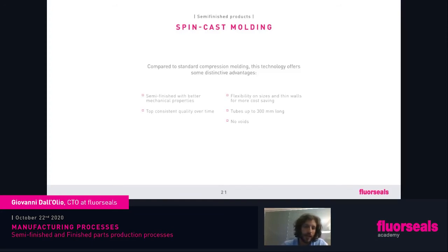But compression molded material has some weaknesses. For example, the mechanical properties are good, but they are not good enough. The strength and the hardness of the material is high, even too high for certain applications. So with this technology, spin-cast technology, we were able to solve this problem for the industry. And now we have a very good market for this spin-molded product, which has incredible mechanical properties, almost the same as injection molded items, but with some differences.